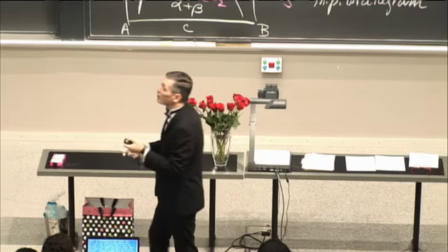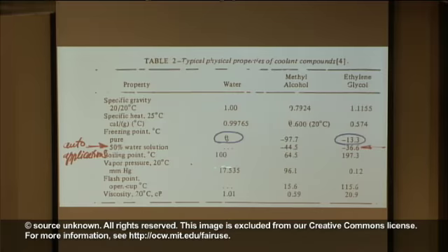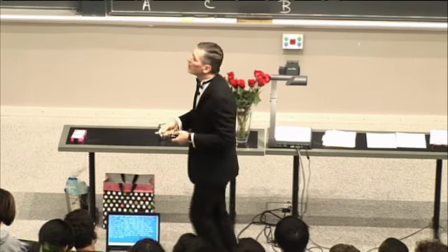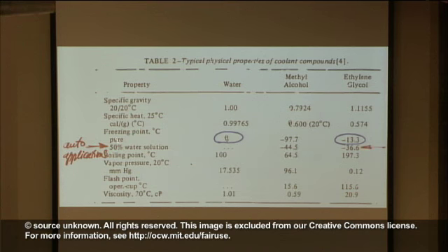All right? But there's another problem here, and that is that the viscosity of water is 1 in these units, centipoise, and glycol is 21. So you'll probably burn out your water pump by running pure glycol, because it's so viscous the water pump is going to be fatigued by running. And here's the point. This is the 50-50, -36 or -37 degrees Celsius.